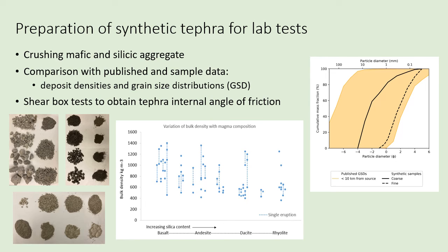This grain size plot shows the same test distributions, and the shaded area is the range of published grain size data for proximal samples up to 10 kilometres from source, and that's the maximum extent of deposition on Ascension before deposits land in the sea. The test distributions are at the finer end of the published range, but I'm focused on uniform loading on roofs, and I'm also constrained by the size of the lab equipment, and so I'm not considering clasts above 16 millimetres in diameter. I've also done shear box tests to obtain the internal angle of friction of the tephra, which I found to be 36 degrees. This is much higher than the angle of friction of the load cell I'll be using, which is around 6 degrees, and so I can be sure that any sliding is controlled by the tephra rather than by the cell.